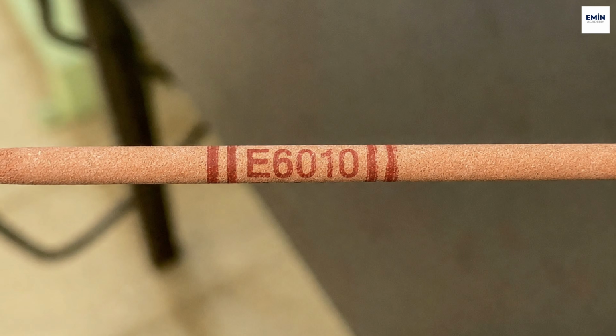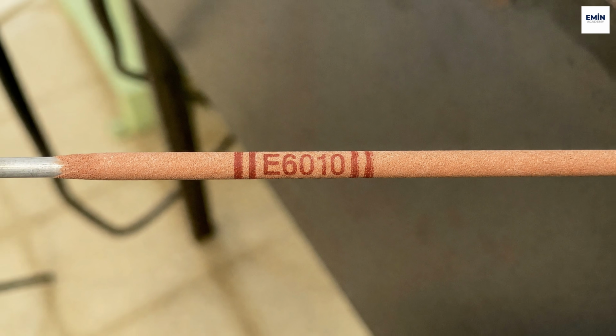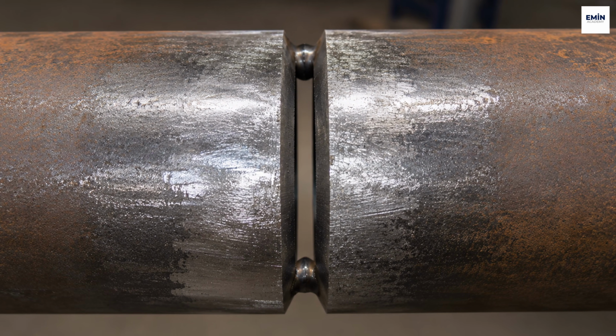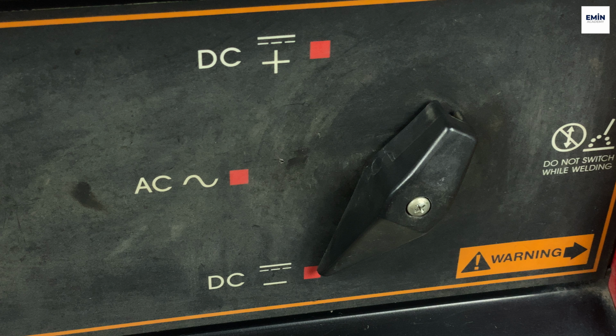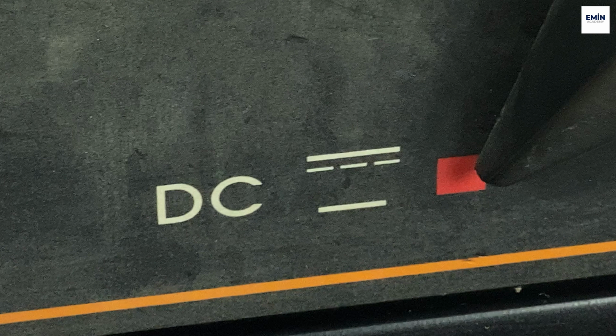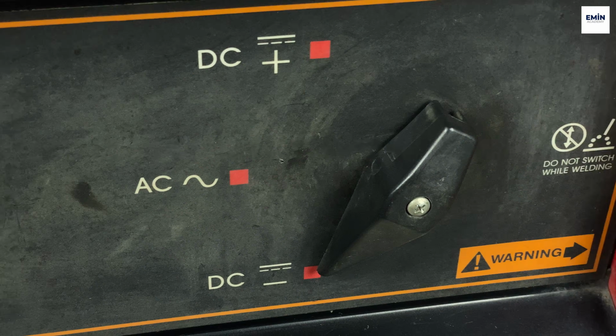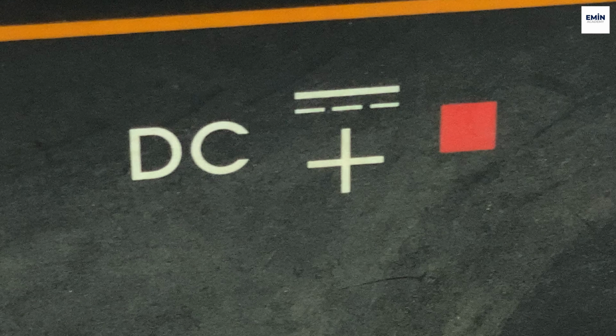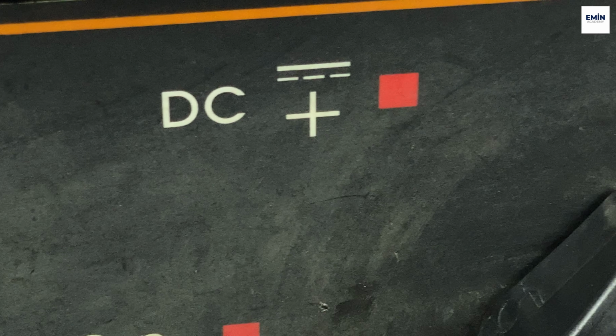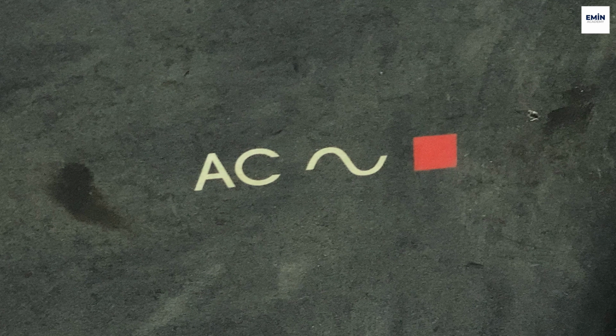0, cellulose-coated electrode. The E6010 electrode is an example of this. It's generally used for the root passes of pipes. It provides very deep penetration. It has low slag. In root passes, direct current electrode negative polarity is used. In fill passes, direct current electrode positive polarity is used. It's not suitable for alternating current.